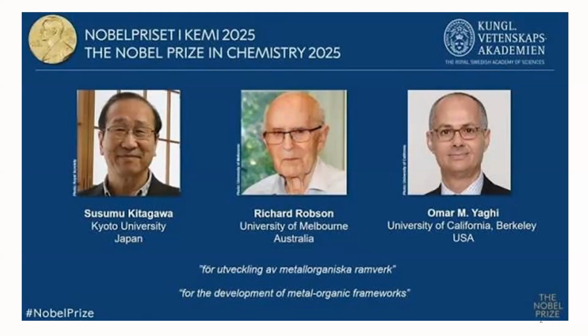Meanwhile, Yaghi introduced a series. The first MOF was MOF-5. This was well used for various applications. And when I came to Valencia in 2008, that was the time people were thinking to use this material for heterogeneous catalysts. Nobody believed that these materials could be used as heterogeneous catalysts, but we were the first to demonstrate that these MOFs can be used as a solid catalyst, especially for performing Lewis acid-based catalysis or redox catalysis. We were the first group to report in 2009, and earlier there were only 2 reports.